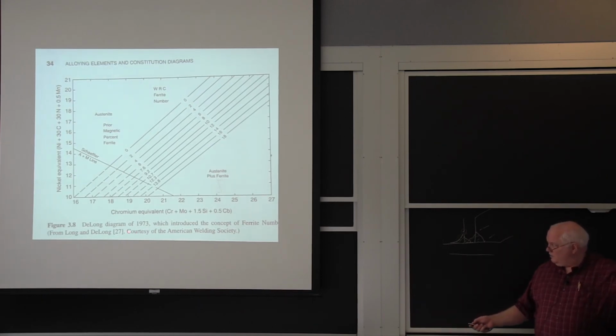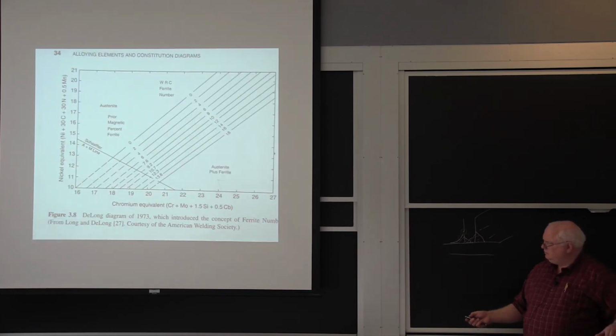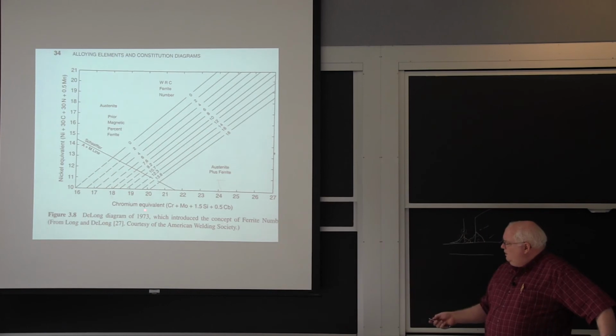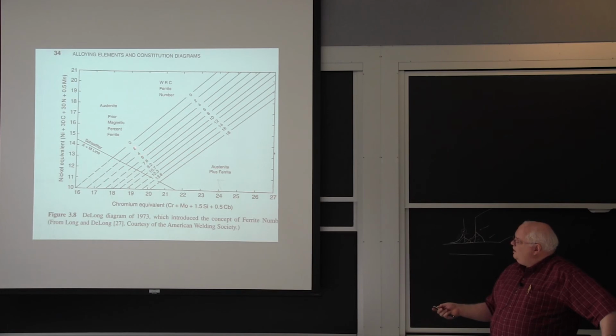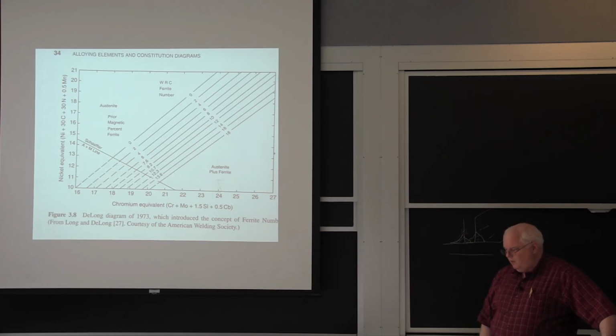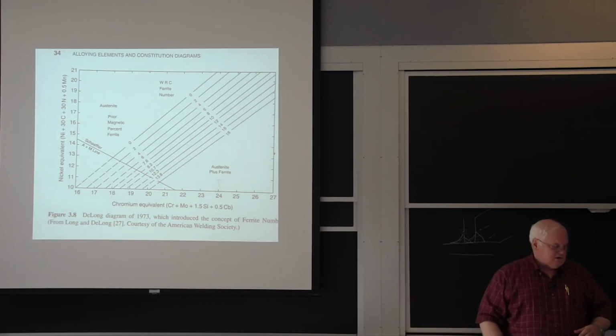Okay, so then a guy DeLong came along. He was working for, I can't remember, it was Bill DeLong. In 1973, he came up with another plot, and he introduced the term ferrite number to the welding community. Here's the Schaeffler line, here's the 18-8 kind of corner for austenite, and you could look in here and see if you wanted to be 2 or 3% or 6% ferrite in your weld metal to avoid cracking. This could allow you to calculate what you should have, how much dilution, what type of welding electrode. So we tend to use 308 or 309 welding electrodes for different thicknesses if you've got heavy section stainless and you don't want it to crack.